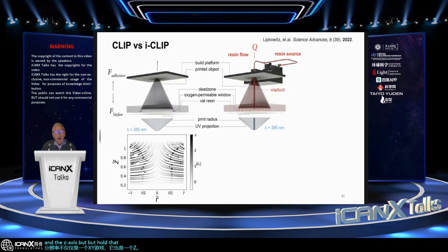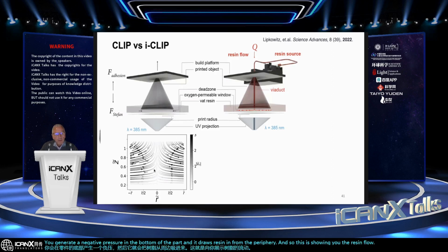But hold that thought. We recently developed a process that's a cousin to what we started with. Remember I showed you the chemistry and physics of the CLIP process: as you pick a part up, you generate a negative pressure in the bottom of the part, and it draws resin in from the periphery. And so this is showing you the resin flow from the periphery to the center of this conical shape here.